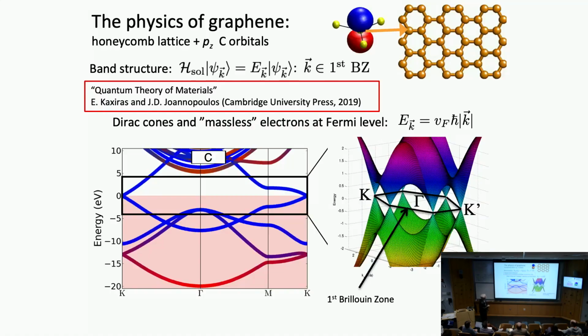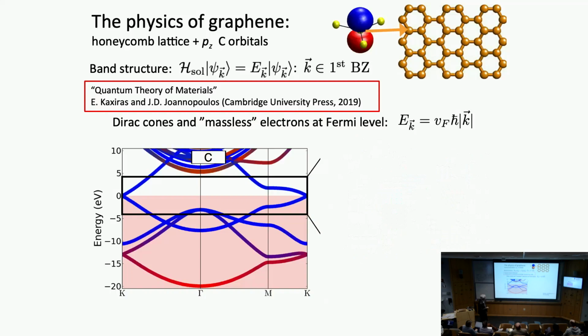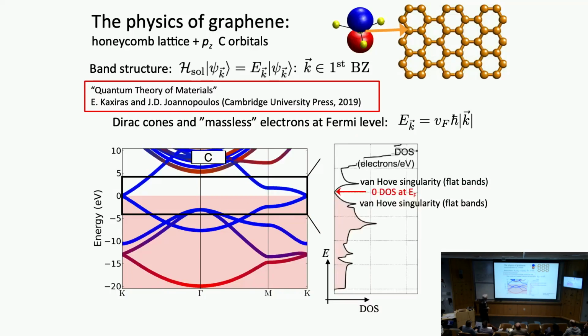Essentially, by solving the Schrödinger equation in the first Brillouin zone, the Brillouin zone is outlined here by this black hexagon, you find that the energy of the electronic bands near the Fermi level at 0 is linear in the momentum. And that was a very exciting discovery. And of course, when you plot the energy as a function of the two components of the momentum, kx and ky, it forms these so-called Dirac cones, linear behavior near these points, near the corners of the Brillouin zone, the K points. This was very unusual and produced a lot of excitement in the physics community.